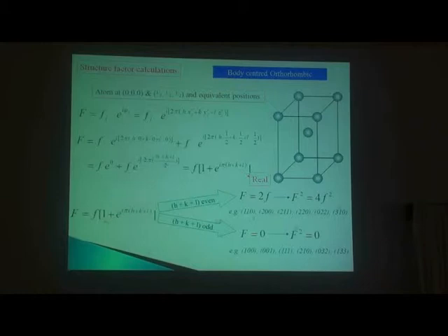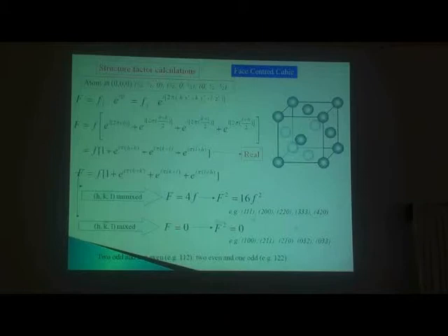Similarly, when you have a body center, it is exactly at the center. Apart from 0, you have half, half, half. You get zero when the sum takes odd values, and maximum when the sum takes even values. That is how every alternate reflection in certain crystals is missing. Immediately you can identify that it's a body centered lattice. Okay? Now coming to face centered.